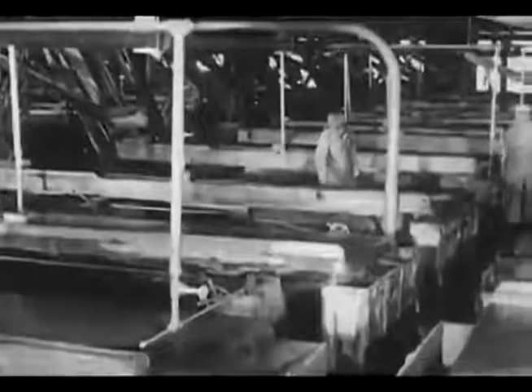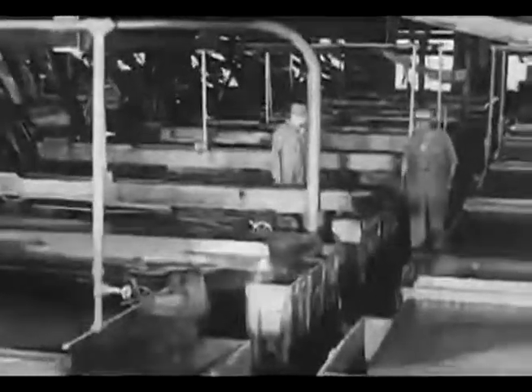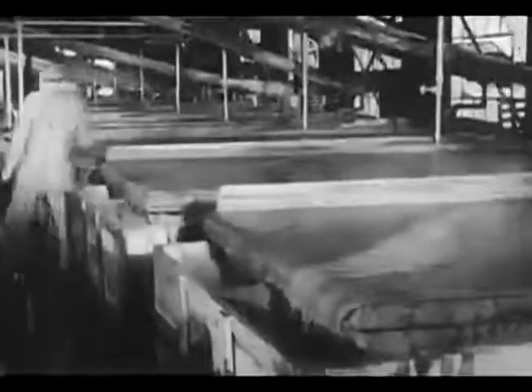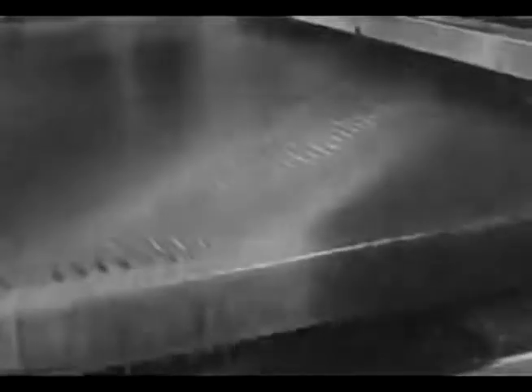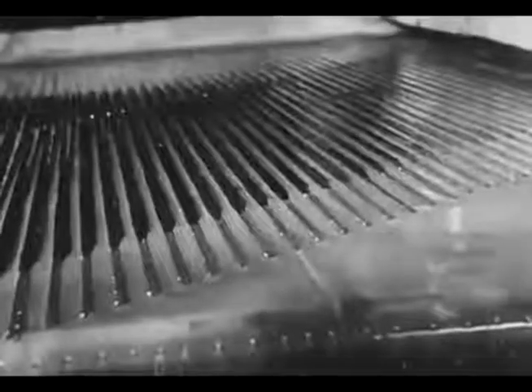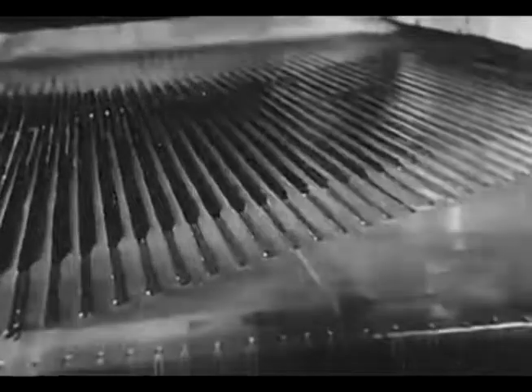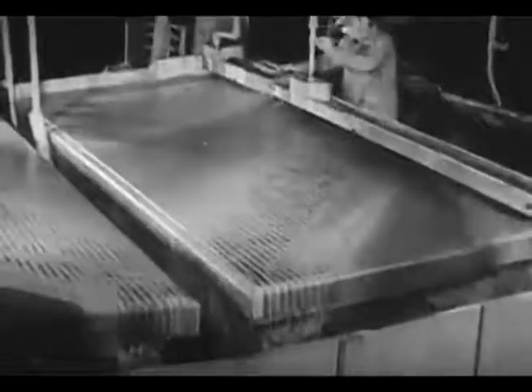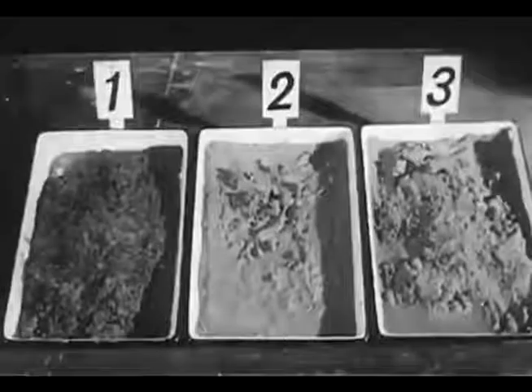The different sizes of classified sands are treated on concentrating tables to separate the lead from the waste, with various sizes treated on different tables. Clear water flows constantly over the deck. The motion of the deck causes the galena — indicated by the dark area — to separate from the waste and discharge from the end of the table. Long, narrow strips of rubber called riffles divert the mineral particles, while the waste flows over the riffles and discharges from the side.